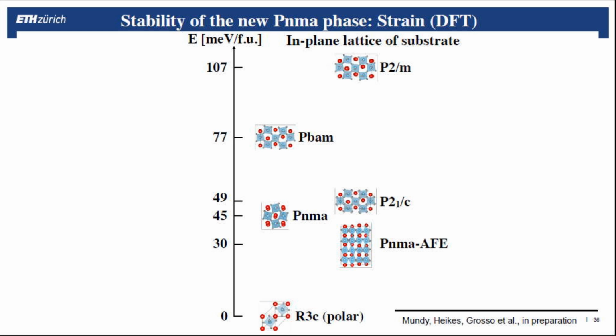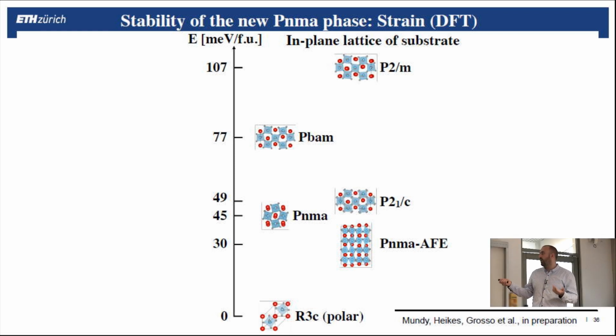So now we identified the structure, but we need to understand why this is the structure that appears in the experiment and not the ground state, which would be just polar. So the first way to check is to think about the strain. You saw that we said that when you apply strain, you can change some properties. So let's consider here different structures and fix the in-plane lattice to the substrate that was experimentally grown, and put the zero energy for the lowest energy one, which is still R3C.